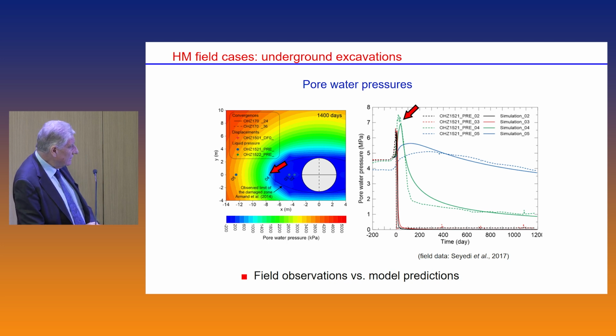For instance, here in dashed lines are observations of pore pressure in a horizontal profile at increasing distances from the opening. Contrary to what you get if you do an elastic analysis, a maximum pore pressure generated close to the opening, here the maximum one is towards the edge of the EDZ, because this part, as we have seen, is relatively well drained. And we can see that the calculations also show the peak a bit lower than observed, and also a reduction with time, which actually seems to fit observations reasonably well.